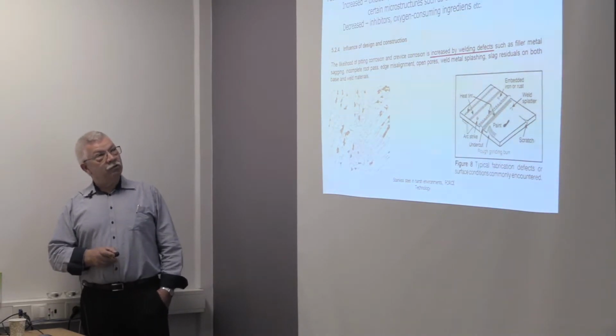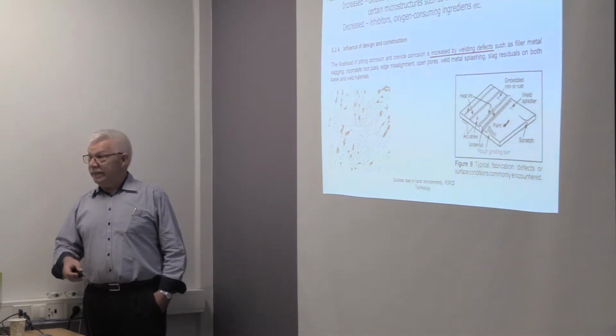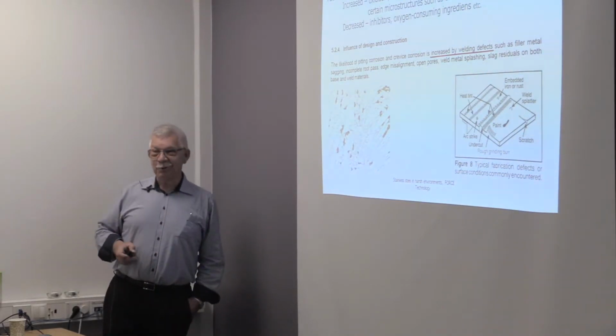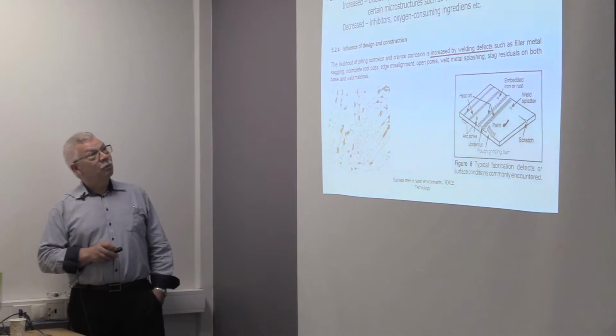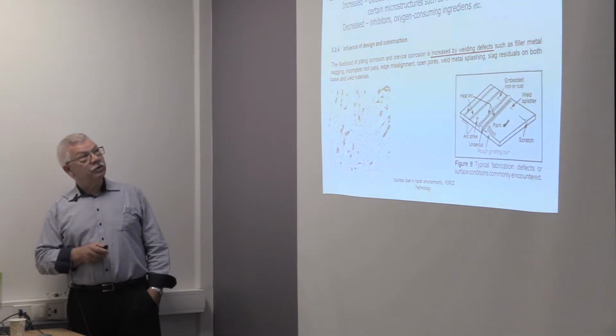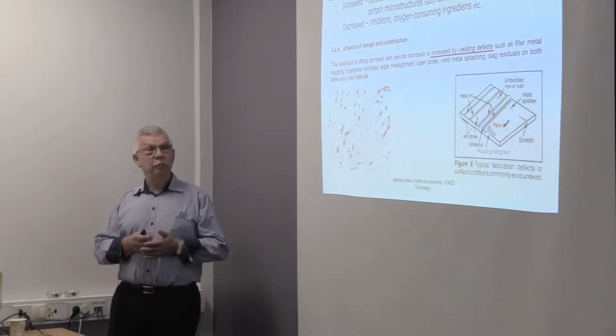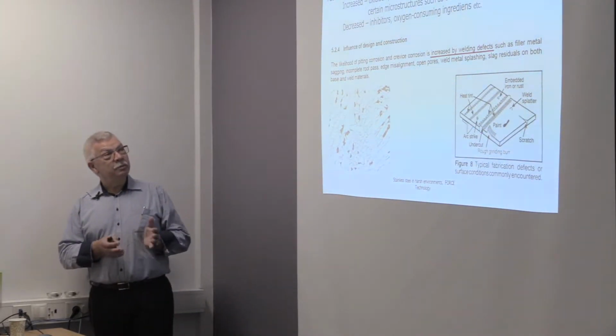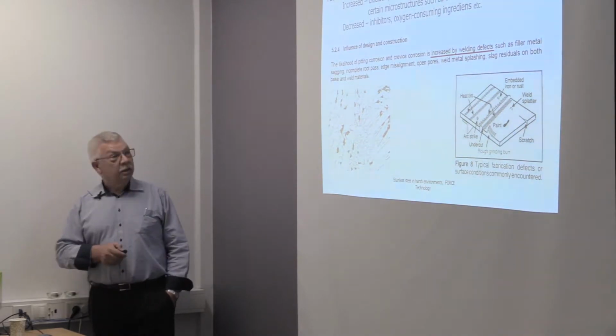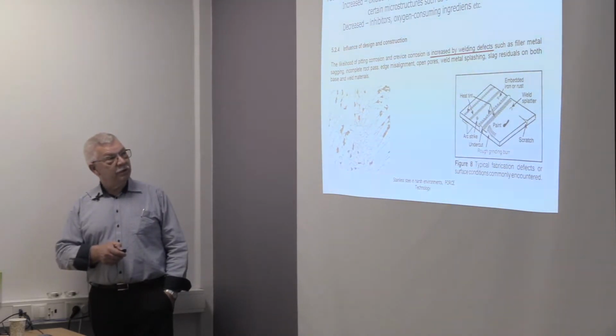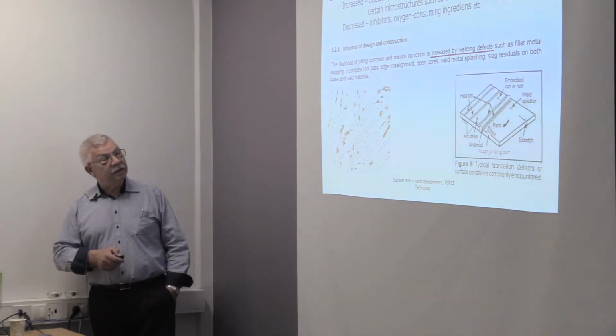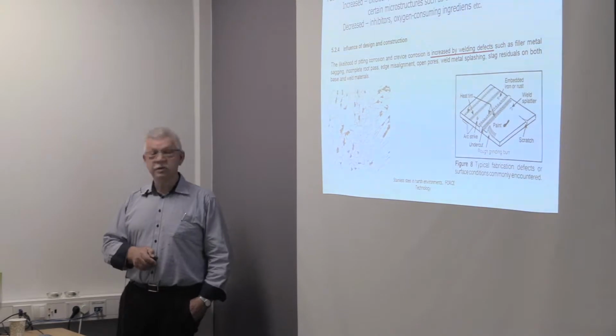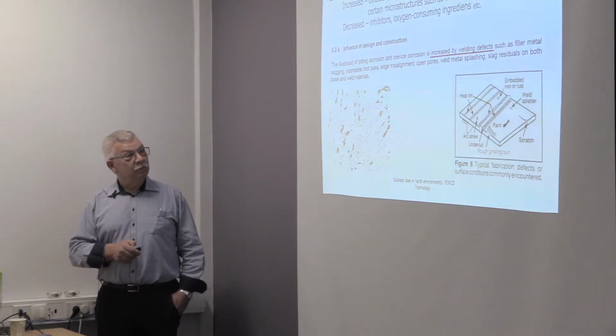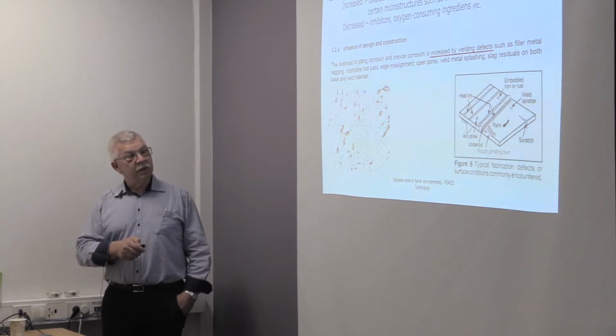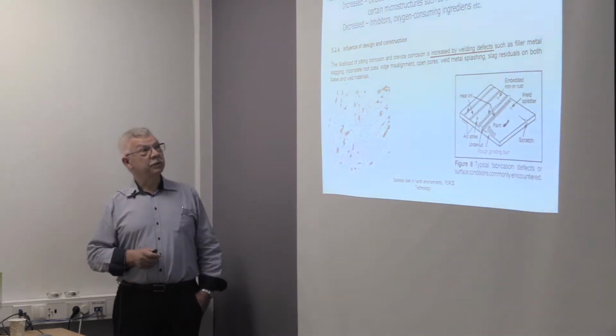We also might have microstructures forming in the material from the heat during welding. At least the arc welding processes where we have melts, we will have different structures forming in the weld material. I'll come back to that. And the heat might transform some of the stainless steel, giving us intermetallic phases like the sigma phase seen in this structure. It will give a significantly lower corrosion resistance. And the reason is that chromium is going into these particles, and you will have too little chromium around these particles to keep up the resistance of the material.